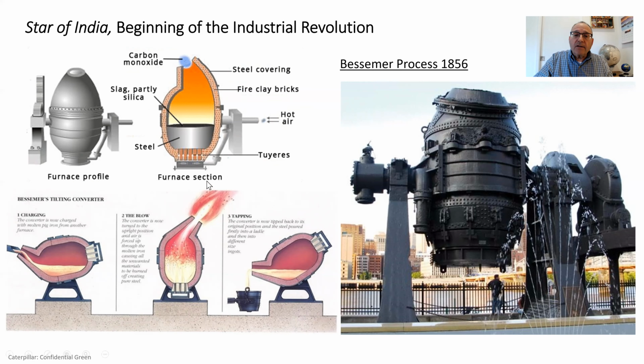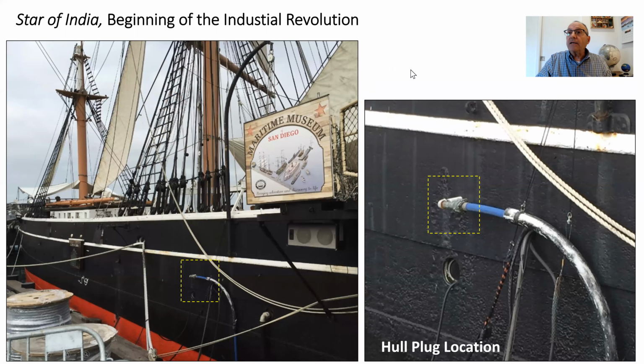So now let's look at what I was able to get from the Star of India. Ideally, I wanted to get at least 2 samples from 2 different locations on the boat. I also wanted to do a microstructural examination and a chemistry to see if I could distinguish whether it was the open hearth process or the Bessemer process that was used to produce the steel that the Star of India has. So here's where I got 2 samples. One is they had drilled a hole in the side of the hull and pulled out a plug. And so this is the location right on the side of the ship where they put this pipe in, and that's where the plug location was.